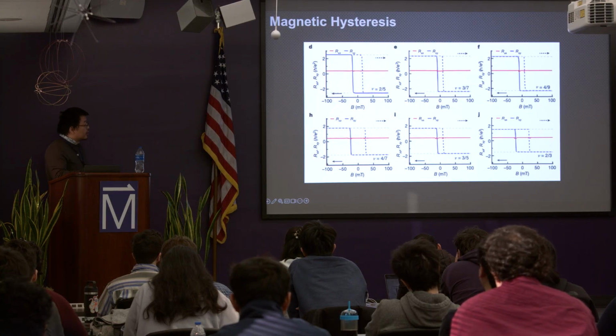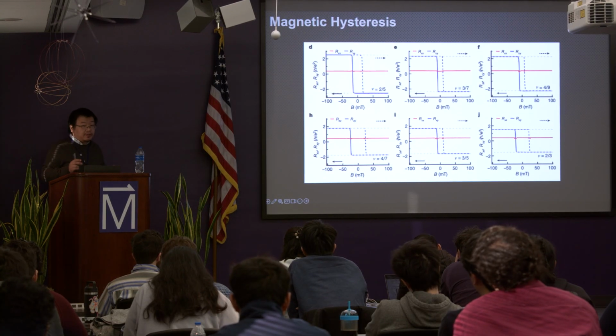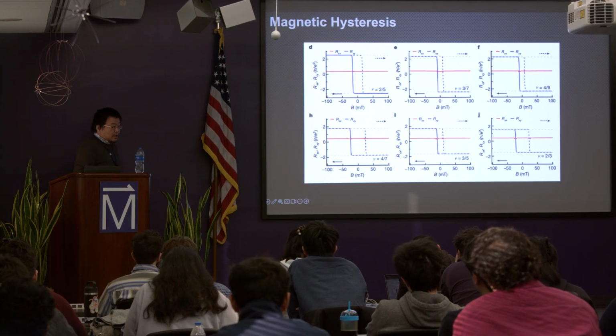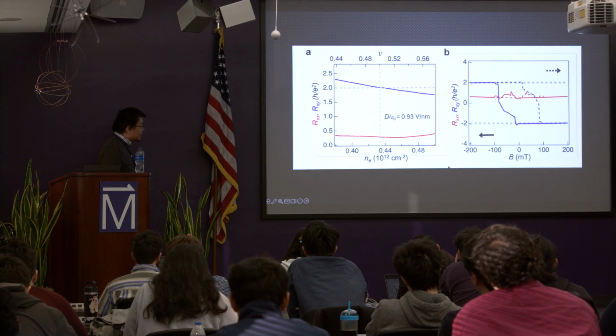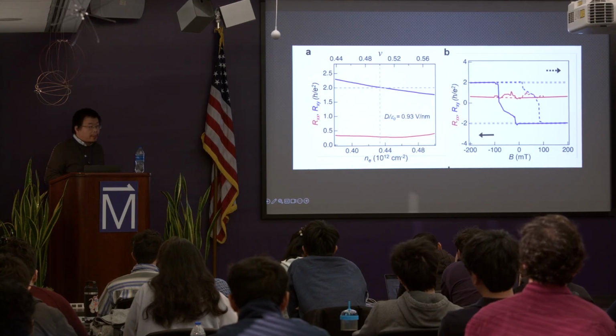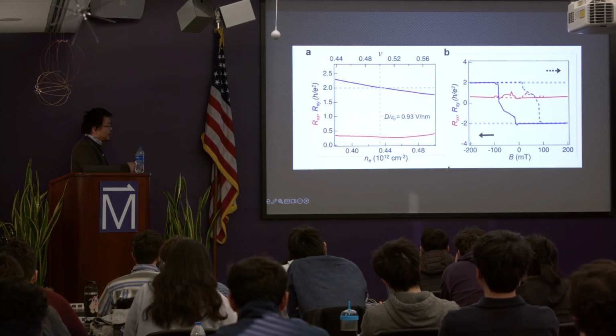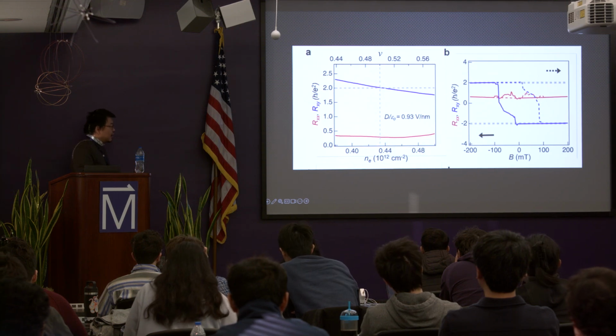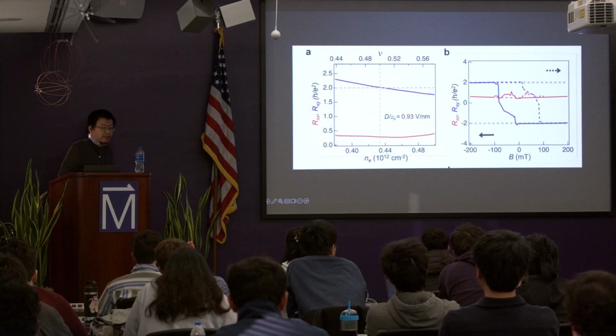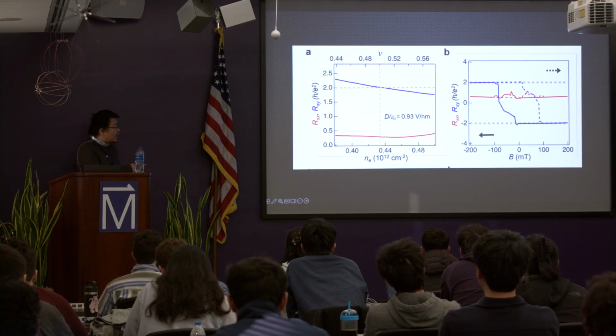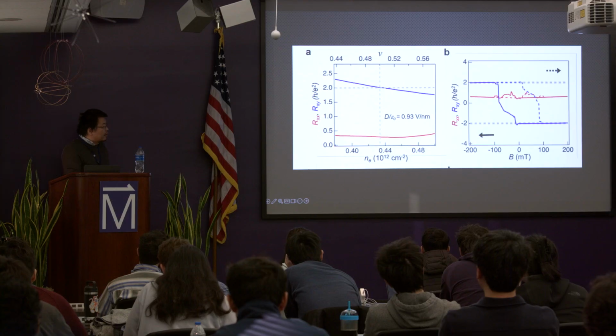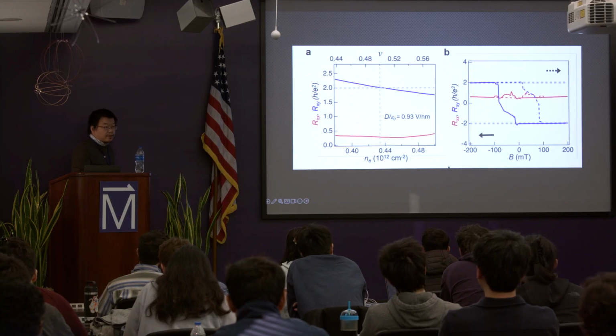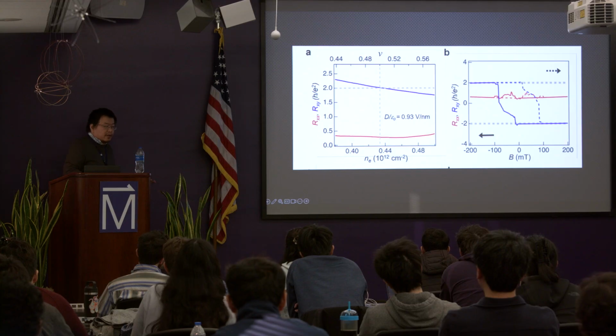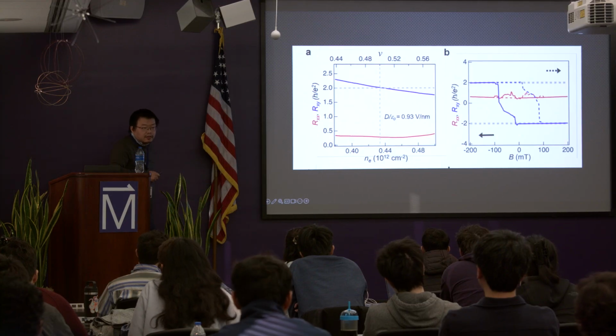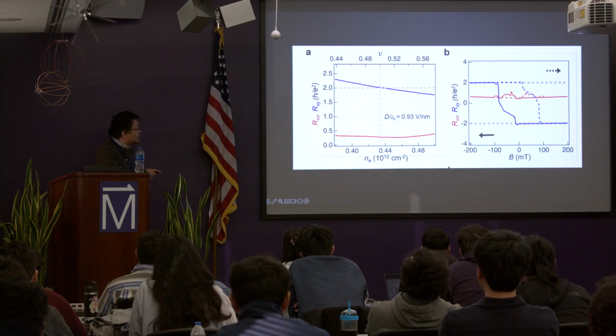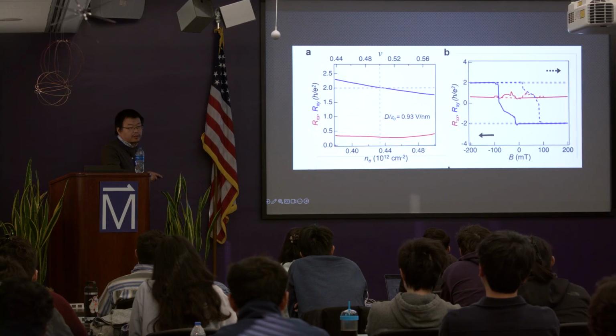But one should be careful here, because the hysteresis loop is actually not a very good indication of quantization. What do I mean by that? For example, I take a measurement around 1/2. On the left side, you have Rxy, which is a tilted line, and Rxx is a relatively flat line. If I'm sitting at filling factor 1/2 and do magnetic hysteresis, it also aligns pretty well with 2h over e squared. But you cannot call it a fractional quantum anomalous state, right? It's not really quantized. There's no plateau in Rxy, and there's no dip in Rxx.